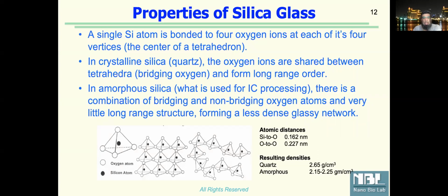You know, when I use silica, silica is nothing but silicon dioxide, another word for silicon dioxide. Now, this would mean that oxygen ions would be shared between 2 tetrahedra, so 2 shapes that are made because of silicon and their binding with the next oxidant. And this would result into a long range order.